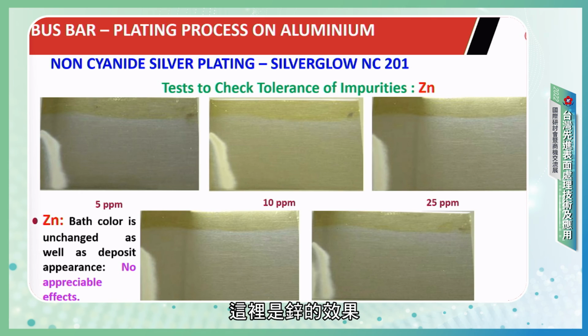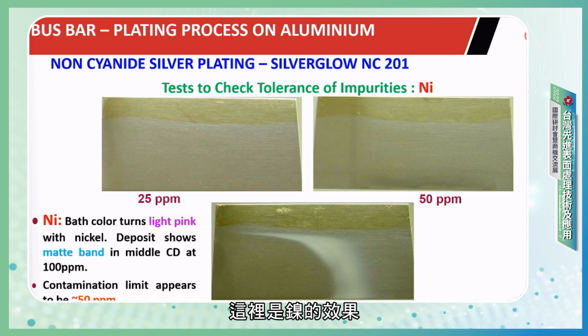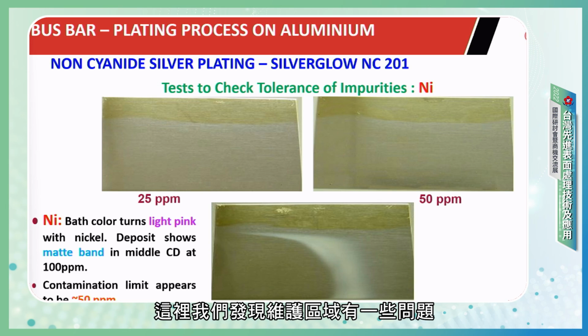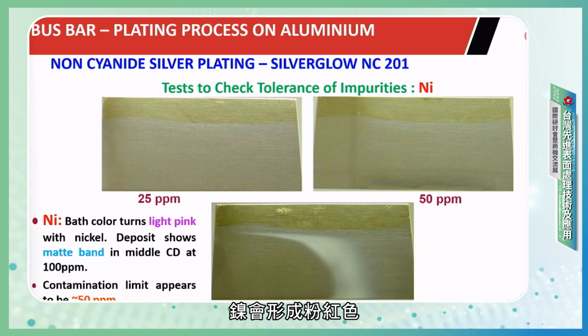Here the impact of zinc is shown, and we don't see much of a defect. Here we show the effect of nickel. We find some issues in the MCD zone, and the solution is getting pink in appearance. So like copper forms blue, nickel is forming pink, so someone can even analyze the impurity without adequate analytical tools.